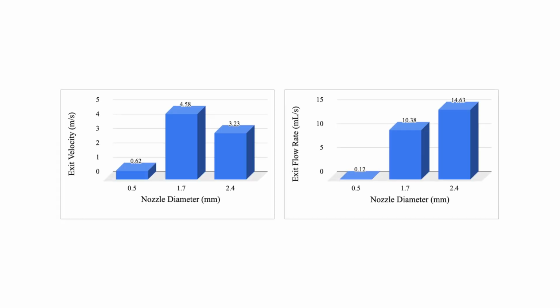Now I want to make sure you guys know that these results are extremely crude. The first two diameters, 0.5 and 1.7, had only one test associated with them each, and the 2.4 millimeter nozzle had two tests. The numbers you see here are an average of those two. However, they had quite large discrepancy between those two numbers, so take this with a grain of salt. But there are some things here that we would expect.